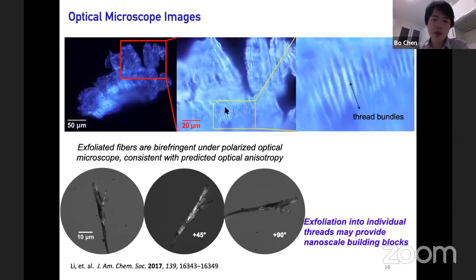Optical image shows the thread bundles on the scale of 20 micron. And these thread bundles can be exfoliated into individual fibers that show birefringence. And this birefringence is consistent with nanothread structure and their packings being anisotropic. So I think from the three previous slides, the characterization established that nanothread has been made under pressure, in this case from benzene. And it's ordered, I mean.